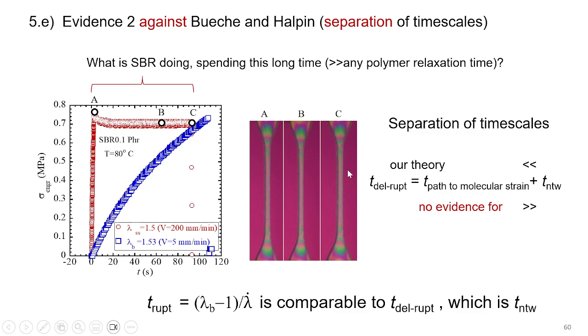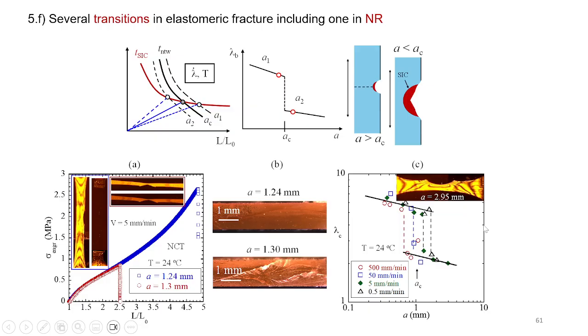And similarly, the system spent most of the time just waiting for the bond to break. There's no change in the molecular strain through birefringence that we can measure. So one of the key conclusions is the separation of time scales. In our theory, it's clear most of the time is consumed by the system waiting for the chain to break, rather than spending the time to reach the molecular strain. So that's one of the key results. I wish I had more time, but I'm running out of time.